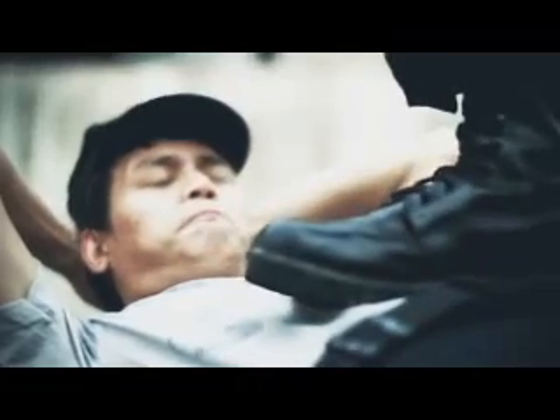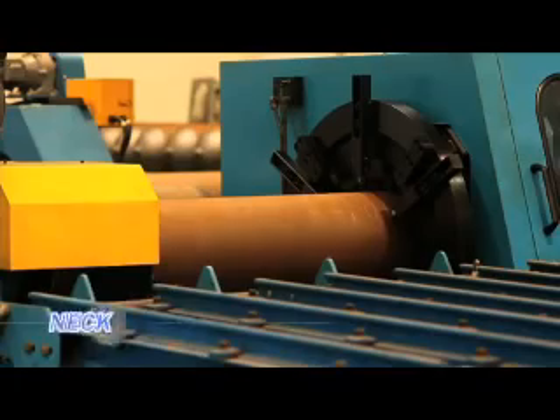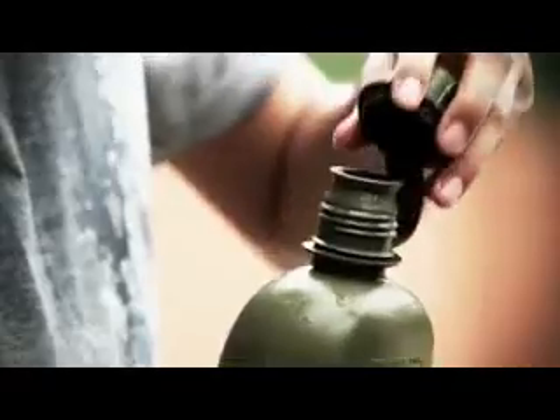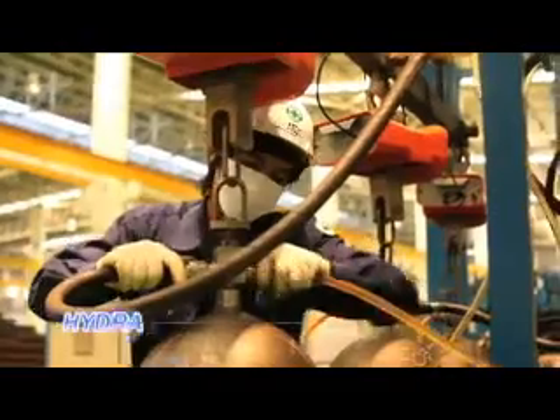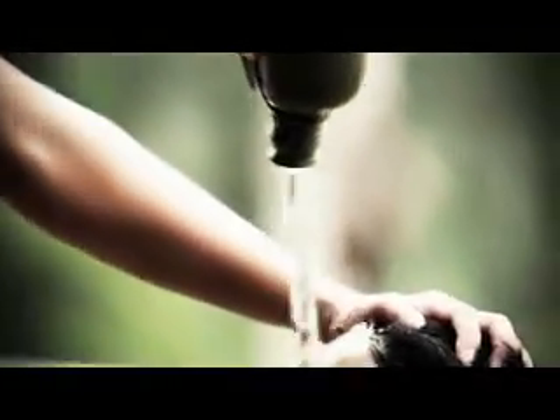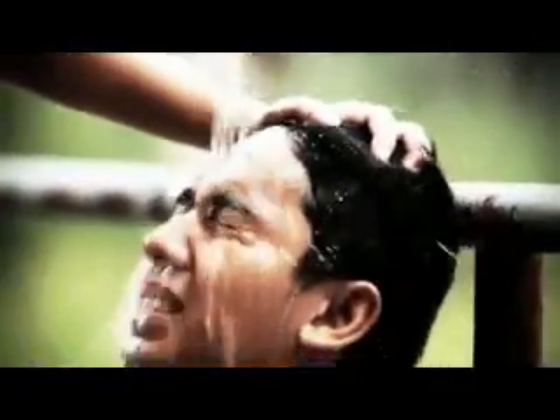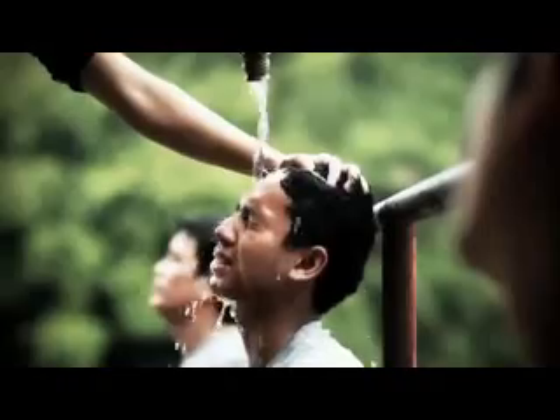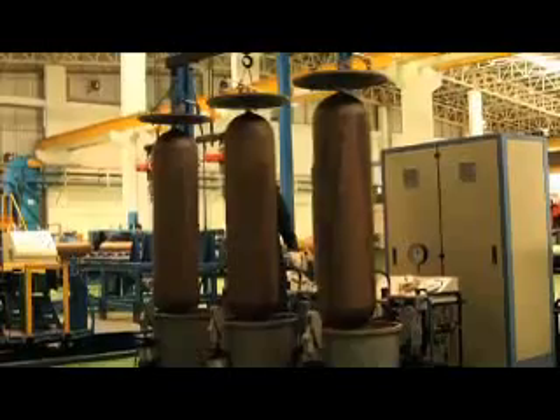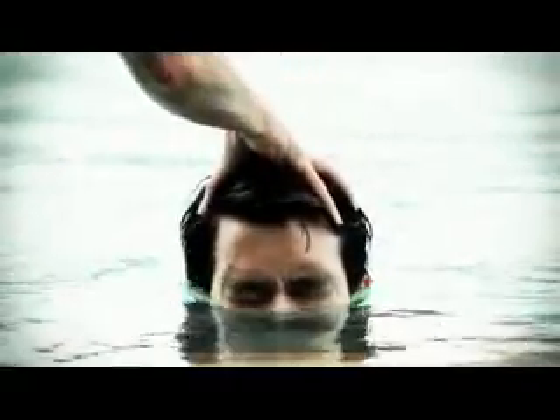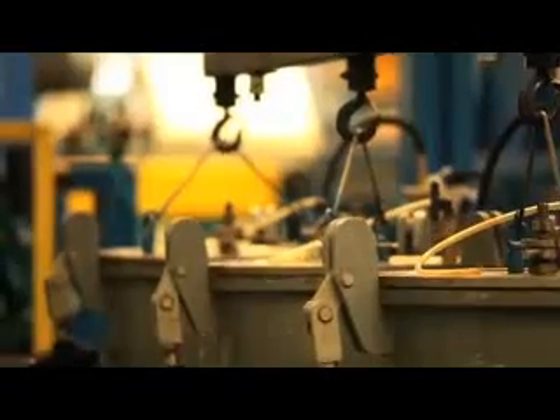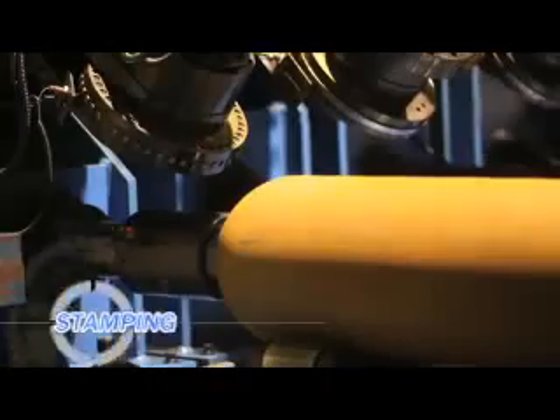Hardness test: measuring the hardness of the cylinder. Neck thread: neck trimming and threading for valve installation. Hydraulic test: pressure testing for the cylinders. Volumetric expansion test at 300 bar for 30 seconds and measuring the permanent expansion. Stamping: automatic permanent traceable marking on the shoulder of the cylinder.